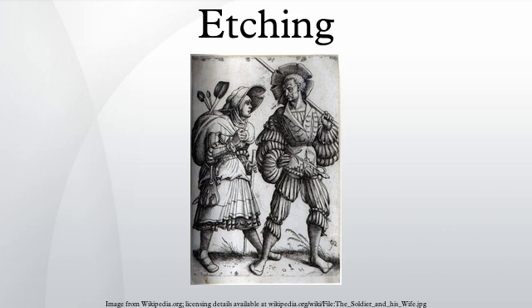Faults. Foul bite or overbiting is common in etching, and is the effect of minuscule amounts of acid leaking through the ground to create minor pitting and burning on the surface. This incidental roughening may be removed by smoothing and polishing the surface, but artists often leave foul bite, or deliberately coat it by handling the plate roughly, because it is viewed as a desirable mark of the process.